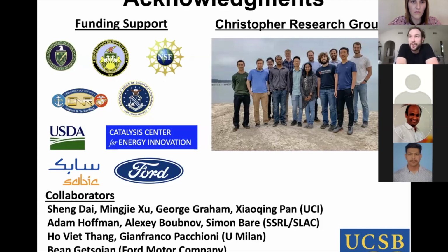Yeah, so actually I know that there is. I didn't talk about it today, and I didn't even really make the relationships, but the relationships should be made, that there are lots of industrial catalysts where precious metals are loaded inside zeolites. Zeolites have really high surface areas, and they also have extremely small cages where you really just can't fit much metal. I know from visiting and talking to folks at Exxon that there are certainly petrochemical conversions where they use fleetingly low loadings of platinum or similar metals in zeolites, such that they want to maintain the cationic characteristics of the metals, and those are really the active sites. So there are opportunities there.